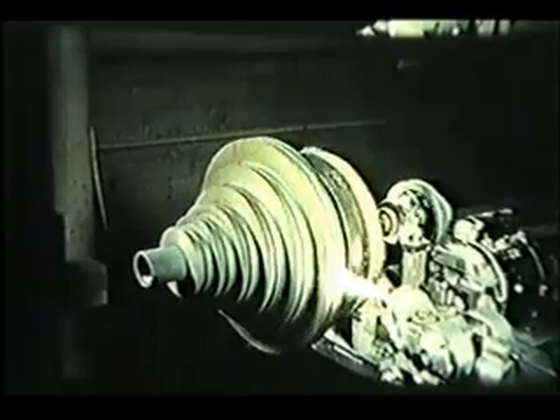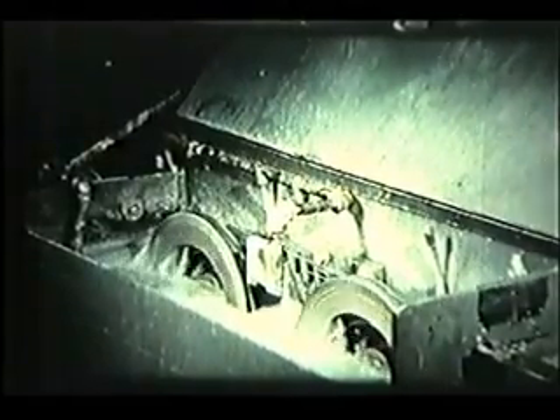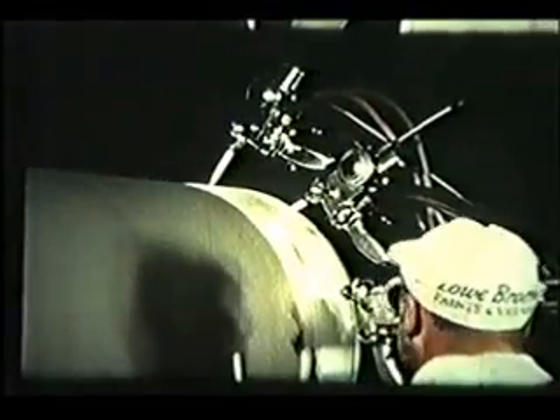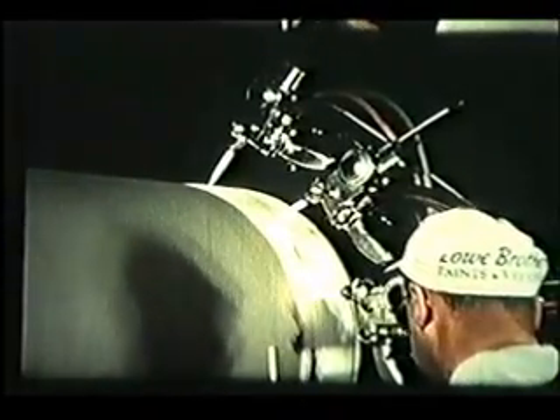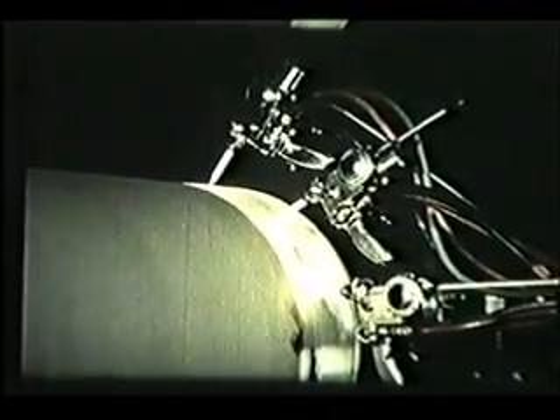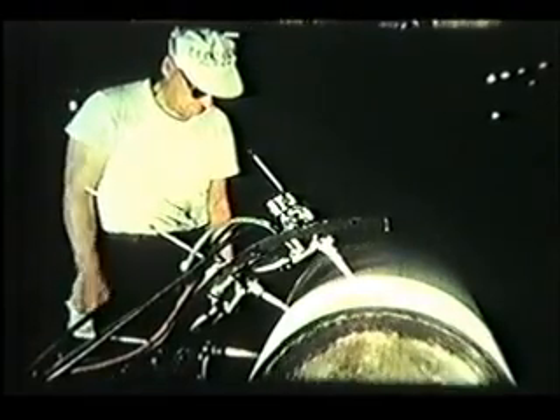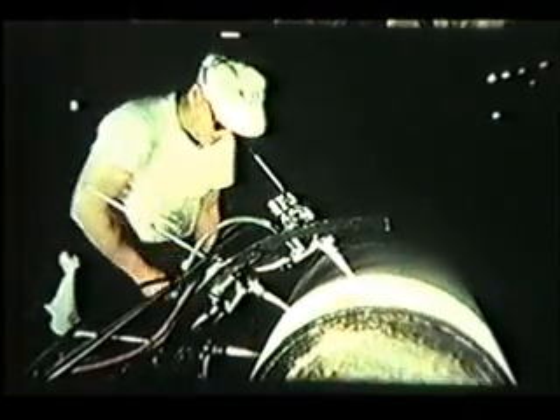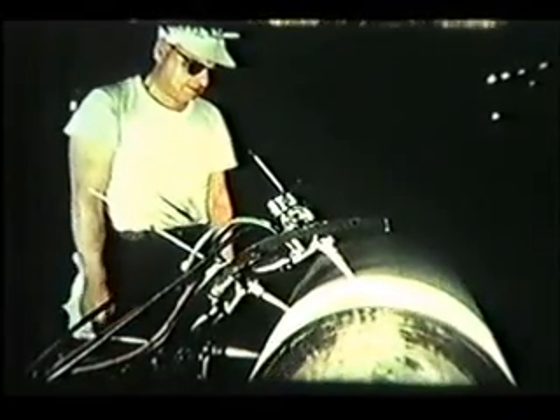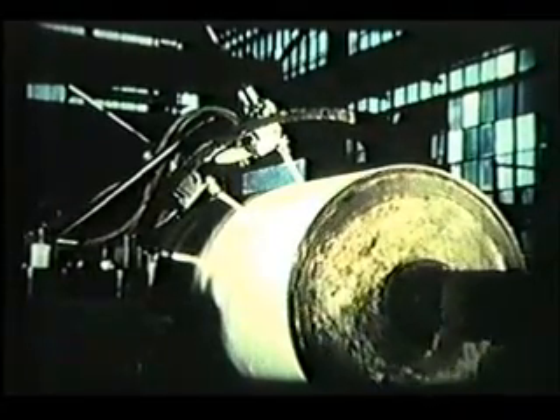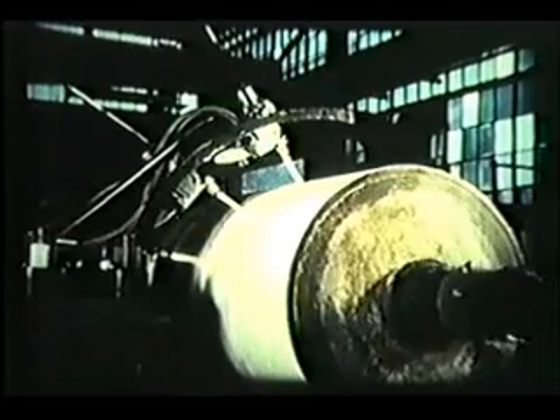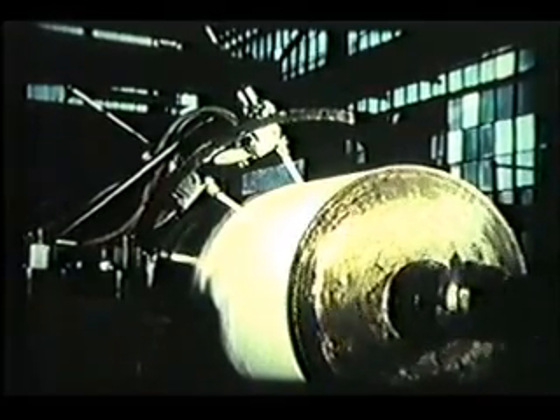Application of Rokide C to the multiple face of a multiple-groove capstan wheel, drawing low carbon steel wire at 1250 feet per minute, improves the wear life of these capstans at least 3 to 4-fold while reducing equipment downtime. To help the paper industries develop a press roll of superior wear life and to reduce so-called fiber pickup, Rokide A is shown being applied to the steel with a 3-gun arrangement. Following the coating of 50 thousandths of an inch thickness, it is ground with a silicon carbide grinding wheel to 35 thousandths of an inch thickness, and results to date show excellent promise.